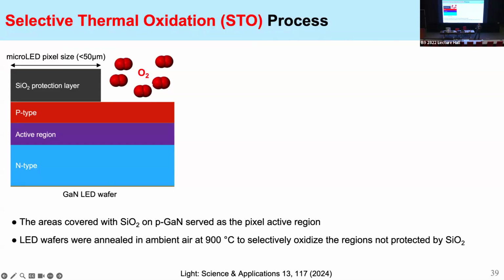And then we can heat it up, because the silicon oxide protection layer can prevent the oxygen from diffusing into the area below. So it basically defines the pixel size. If we make it 5 micrometer, the LED will be 5 micrometer. If it's 50 micrometer, the LED will be 50 micrometer.